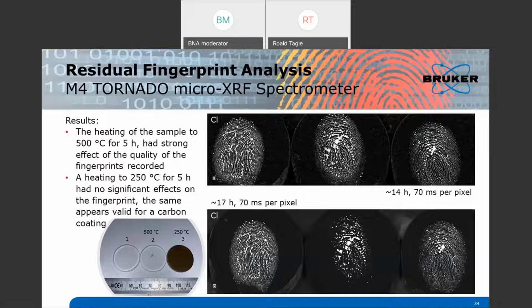So apparently, and this is just a basic experiment, it's not intended to be a proof or a full validation of the procedure or of survival probabilities of fingerprints, but it seems to be an indication that fingerprints tend to decay depending on the high temperature. The higher the temperature, there seems to be some process that tends to eliminate, or destroy a little bit, the information of a fingerprint. However, heating up in our setting under the given conditions, 250 didn't do any significant change to the fingerprint. That's what we wanted to show, besides showing the possibility of the instrument to present the fingerprint, just to look a little bit more at the possibilities in situations where you might not be able under conventional settings to get good fingerprint results.